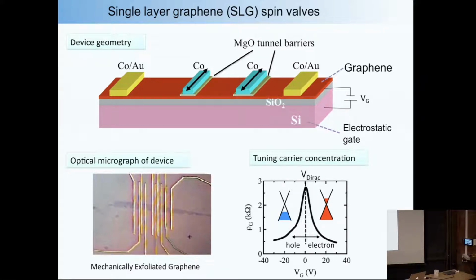So here's a strip of graphene, and then there's a bunch of metal electrodes. These are all cobalt. So the big trick was, ideally you want to have these to be gold, but if you're Bart van Wees, you're very smart and you just make them all cobalt. So you have huge numbers of sets of 4 to do your experiments on. And the fact that these outside produces some extra junk is not that important, initially anyway. And the other point is that if you apply a voltage to the gate, this is like a capacitor, and what happens is that if you put a positive charge on there, it will attract electrons into the graphene.